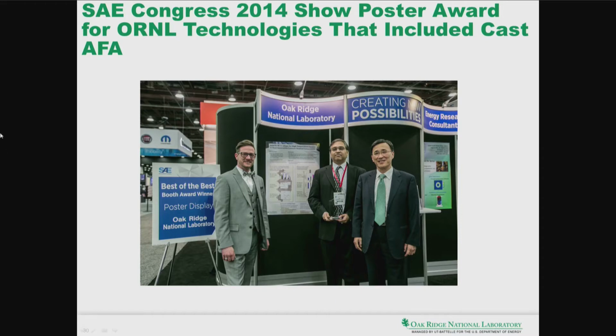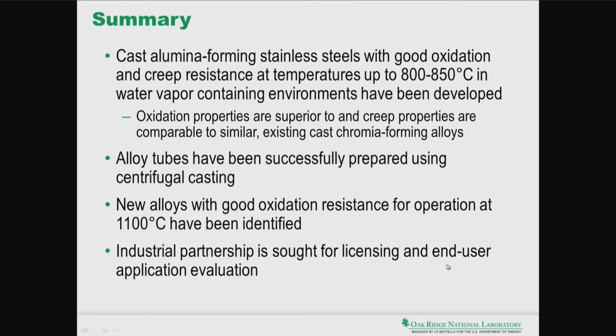So we presented some of these results at the SAE meeting, and we did receive a good response; the benefits of the cast AFA alloys as they pertain to the exhaust manifold application were appreciated. And in summary, I have shown you that we have developed cast alumina-forming austenitic stainless steels with good oxidation and creep resistance at temperatures up to 800, 850 in water vapor containing environments, and probably pushing up to 900 in dry air.